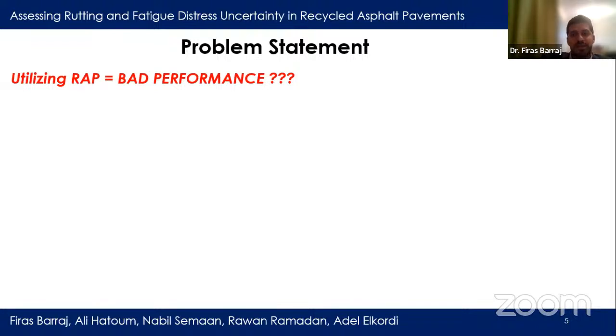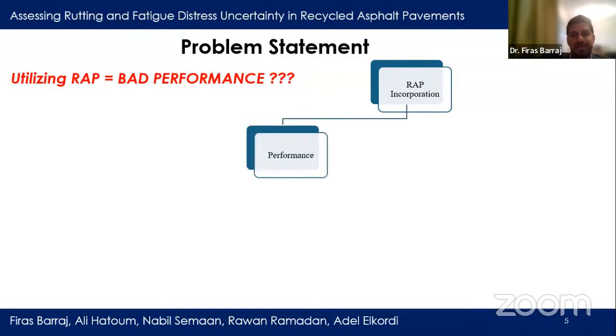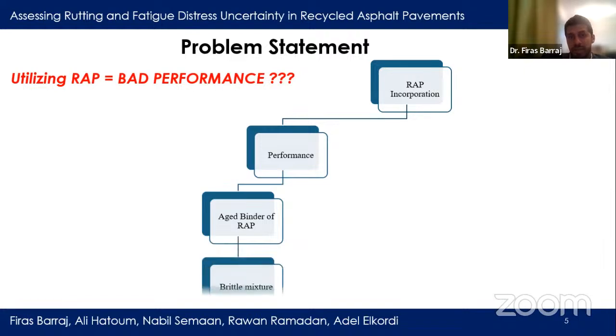Now with the problem statement, will RAP utilization lead to a bad performance? This statement is legitimate since performance doubt exists because of the aged binder of RAP that is typically characterized by a high softening point and low degree of ductility, both of which may lead to obtaining brittle asphalt mixture more susceptible to accelerated damage.